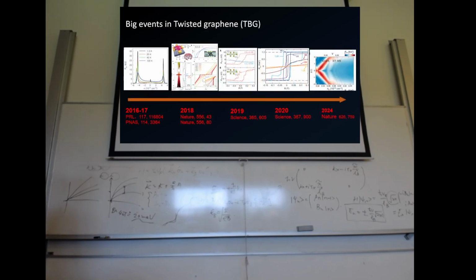When you have partial fillings, you have insulator which is accompanied by superconducting pockets. Whenever you have a sample with this 1.1 degree alignment of twisted bilayer graphene, you have similar results. Depending on the sample quality, people get different pictures, and people try to understand by, for example, applying hydrostatic pressure to the system, and the superconducting transition temperature changes a little bit.